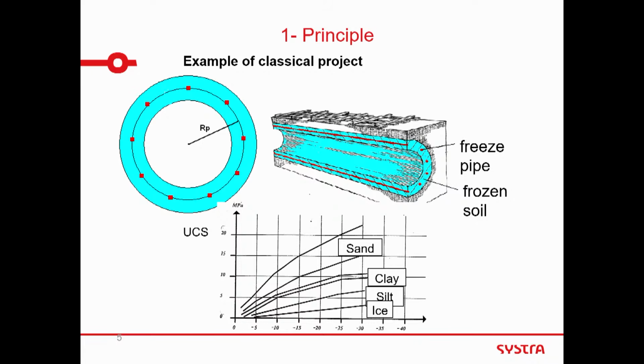And what you can notice from lab test is that the UCS, the unconfined compressive strength of this frozen body, in fact, decreases when you get more clay and silt, so small size particles. Okay? You can see that, for example, for clay, you get under -10, you get 5 MPa, silt 2 or 3 MPa. What is also interesting is that for ice, pure ice, UCS is kind of lower than the mix with the soil. Okay? You take these values for short term, because the story is a little more complex, but if you take a frozen soil directly, you test it in lab, you test it quite fast, obviously, you are not going to wait to load the sample, you'll get this strength.